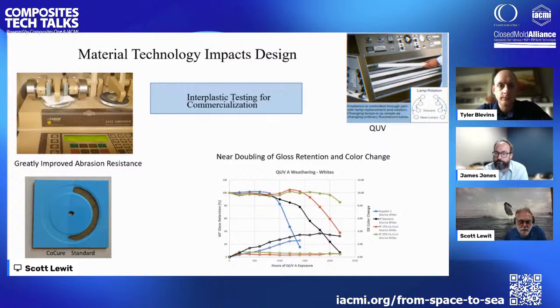And then the other thing that we're really lucky on too is polyurethanes have, the A side is kind of nasty, right? The A side of polyurethanes has a lot of potential environmental health consequences. And it turns out the amount of ISO, the A side, that we use is so small that in all the testing that's been done at numerous factories now, it's undetectable. So you're getting the low HAP and you're getting low ISO. That was really fortunate for us.